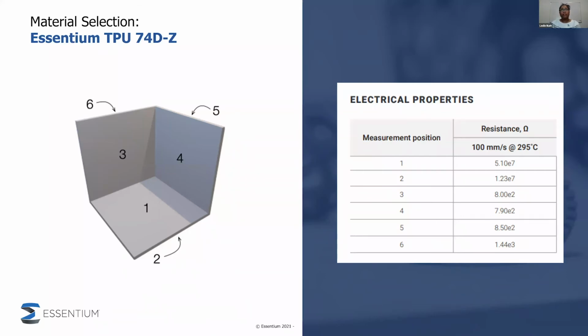So you can find some of the ways that we test for the electrical properties in our TDS sheets, technical data sheets, for all of our materials. You can find these located at our Essentium website. One of the ways that we test the surface resistance for our 3D printed material is by creating this three-sided cube like you see on the left. So there are 6 sides that we then take a surface resistance probe, touch the probe to each one of these sides, and then we can measure the resistance in ohms. For the TPU 74DZ testing, this was printed at 295 degrees Celsius at 100 millimeters a second.